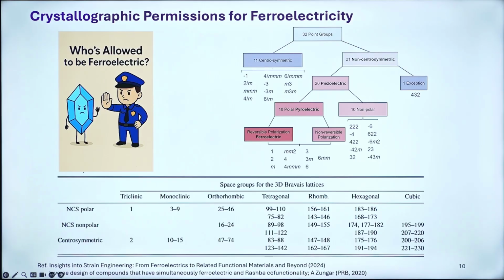So for a theory person we always try to find out a space group which will favor the polarization, okay. Of course there will be a structural transformation, but then we have to be more specific in selecting a particular space group, because these calculations are computationally very expensive, okay. From the literature we will try to see what are all the possible space groups which will favor ferroelectricity, and then you see these non-centrosymmetric polar and non-polar, for which we have monoclinic, orthorhombic has more, and tetragonal, rhombohedral and hexagonal, these are the corresponding space groups, okay.